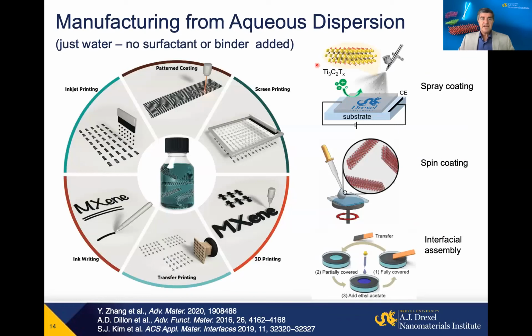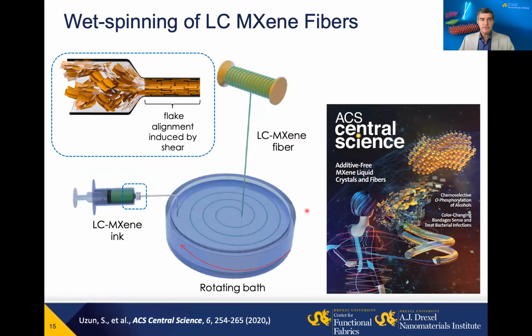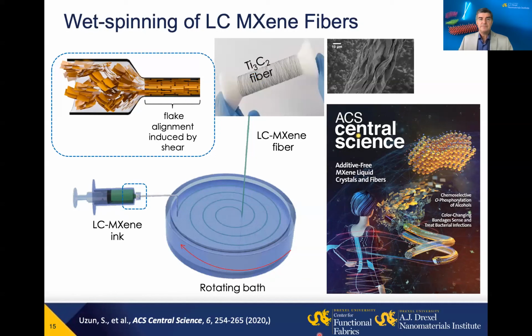So we can use basically any solution processing technique, just as for other colloidal solutions and nanoparticles, and produce a variety of film structures, aerogels, you name it. Anything you can make, for example, with graphene oxide, you can make with MXene, but it's conducting. Moreover, if we take a highly concentrated solution, it forms a liquid crystal. And we can even draw fibers from this liquid crystalline MXene and produce fibers.